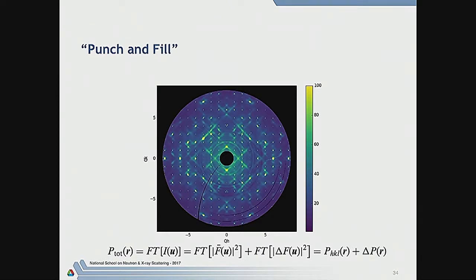However, it turns out that because of the properties of the Fourier transform, you can actually separate this into the Fourier transform of the average structure and the Fourier transform of deviations from the average structure. Now, we know what the average structure is. In Q space, the average structure is encoded in the Bragg peaks at these integer HKL positions here. Okay. So this here represents the Patterson function, which comes from the average structure. And this then represents all the deviations from the average structure.